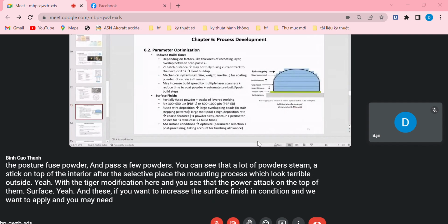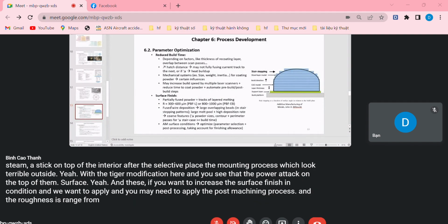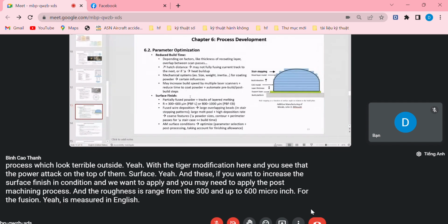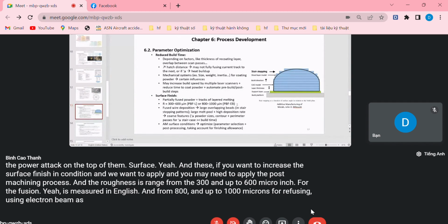If you want to increase the surface finishing condition, you may need to apply the post machining process. The roughness ranges from 300 up to 600 micro inch for particle fusion, measured in inches, and from 800 up to 1000 micro inch for particle fusion using electron beam as the heat source.